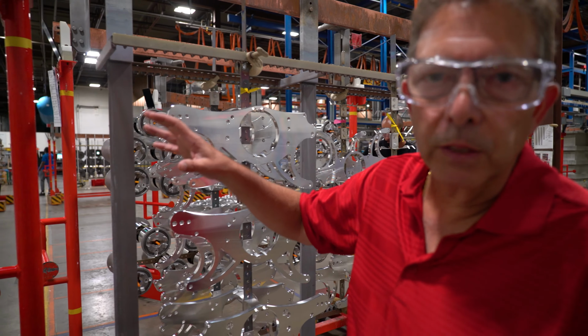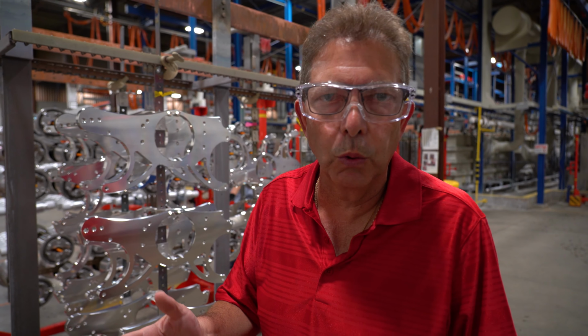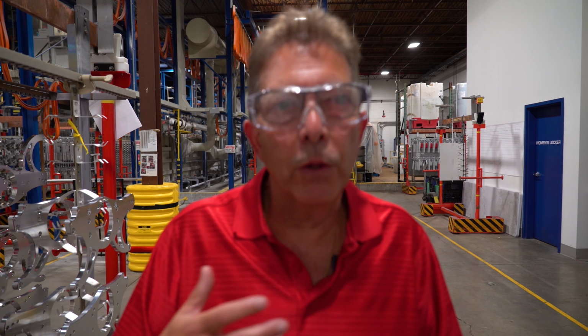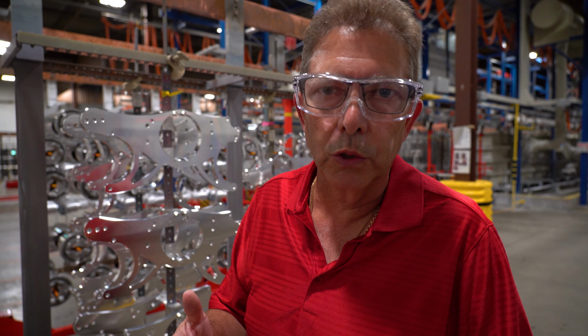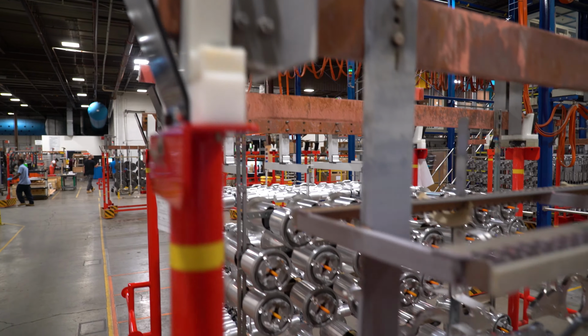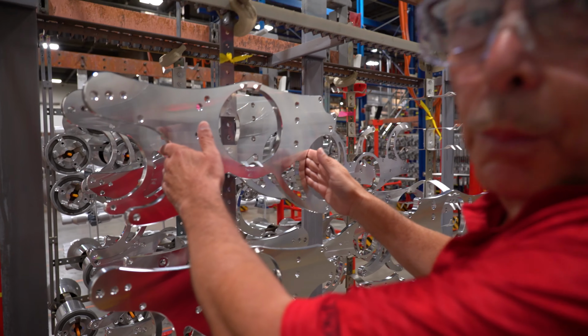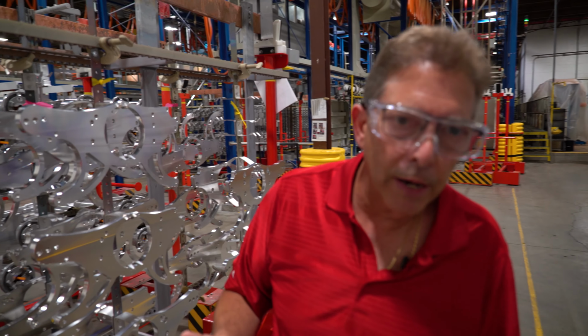When we're racking up parts, we can use one of two items. We can either use titanium tooling or aluminum tooling. If we use titanium tooling, the tooling will virtually last forever. If we use aluminum tooling, it anodizes along with the parts and needs to be stripped before we can use it again. We make electrical contact through the work bar, into the tooling, and then actually into the parts. We need to make rigid contact with the parts to make the contact points, and then the anodizing occurs.